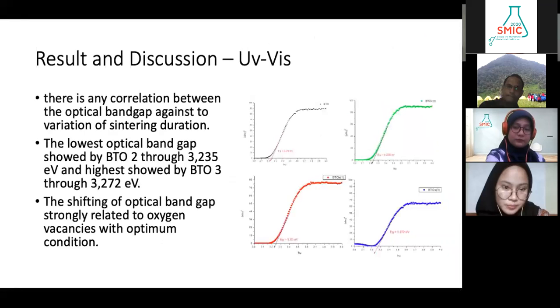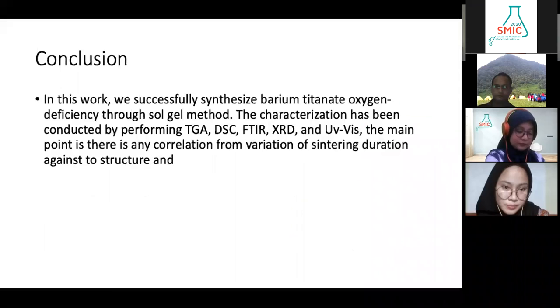Then for UV-visible, there is a correlation between the optical band gap and the variation, because the lowest was shown by BTO2 at 3.235 electron volt, and the highest was shown by the BTO3 sample at 3.272 electron volt. The shifting of the optical band gap is strongly related to oxygen vacancies with optimum condition.